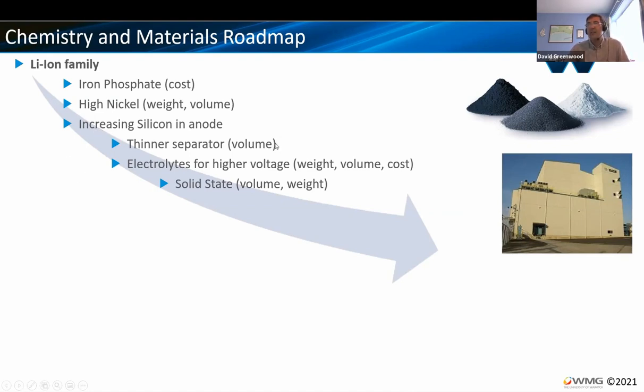Supporting that, we need to see thinner separators, not just to reduce the volume of the battery, but also to reduce the electrical resistance of the battery or the impedance. And that's an enabler for faster charging. We need to start to see electrolytes that don't decompose at high voltages, because at the moment we've got electrochemical materials that would allow us to run quite high voltages in the cell, but the electrolytes won't live through it. So we need to see formulations of electrolytes that let us sweat the best out of the materials that we're using. And ultimately, of course, the trend for this is to move us towards solid state and hopefully get rid of the graphite anode and replace it with a lithium one in the longer term.